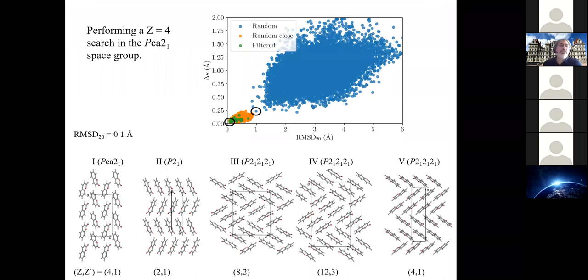And an example of this is this coumarin structure, right? So this is coumarin 1. Here's the blue clusters, our initial set of random structures. Okay? Then the first step is to find the one with the smallest delta S. That's the one I've circled there. And then you generate a new cluster. And I'm only showing you the ones that reduce the value of delta S.